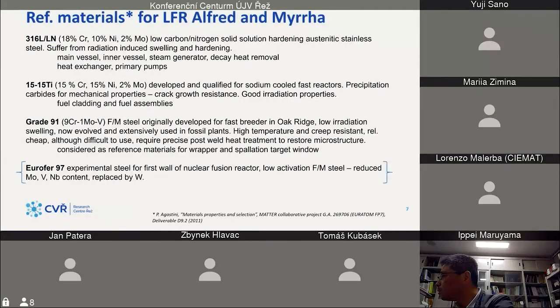The reference material for this reactor is 316L for the vessel, primary pumps, and steam generators. It's a classical steel for nuclear energetics. It's well known and lots of data is already available. But it has a problem with radiation-induced swelling and hardening. For cladding, there is a candidate steel developed for sodium fast reactors. It's 15-15 titanium. It is a precipitation-type steel, and it has good irradiation properties in comparison with 316L.